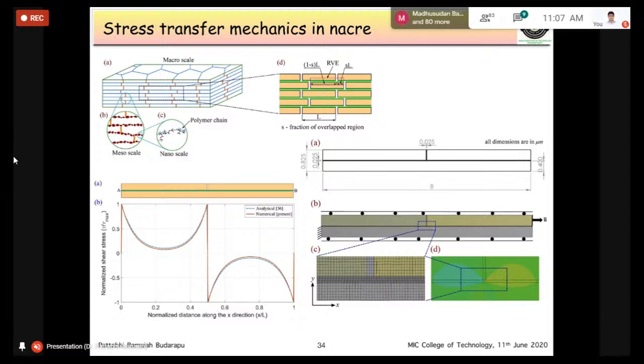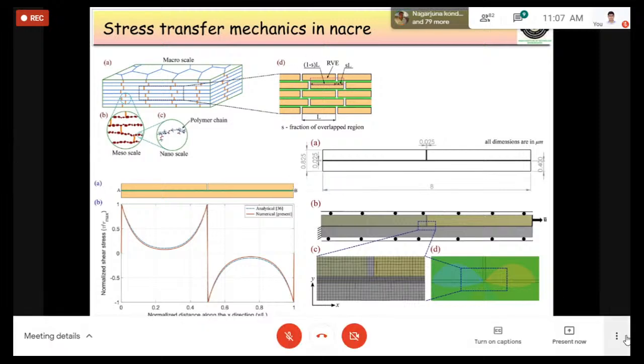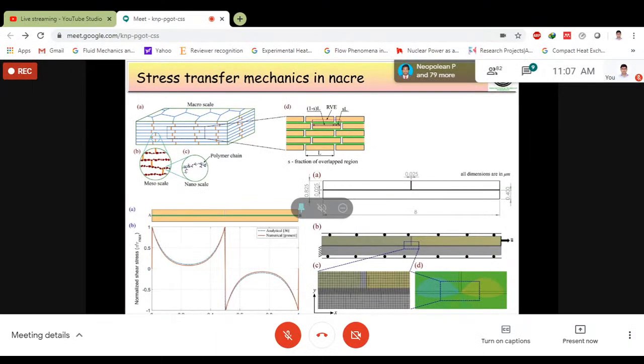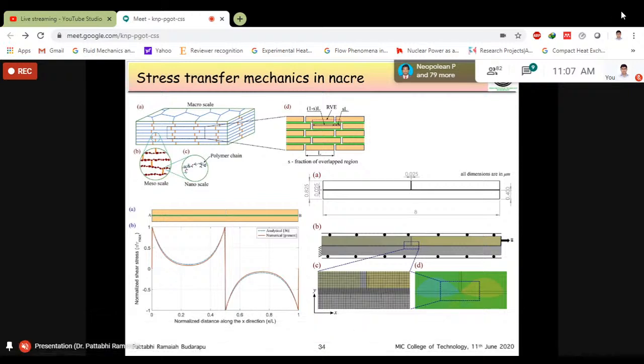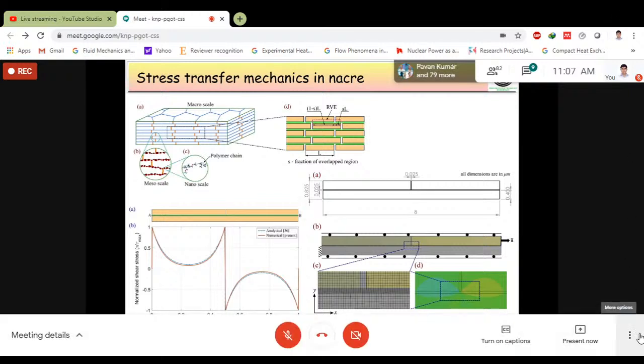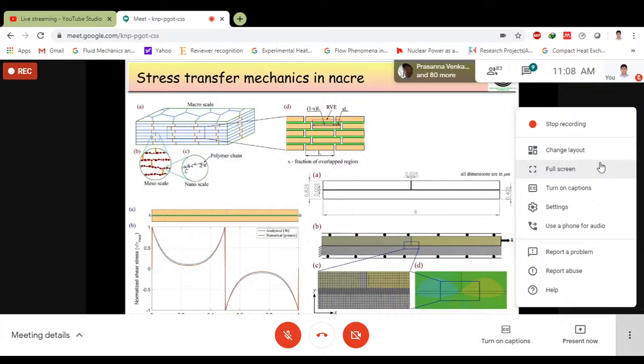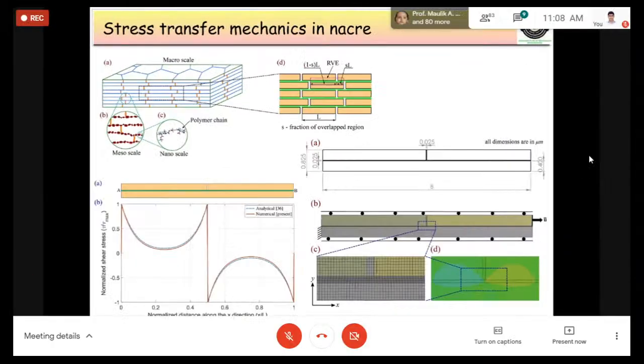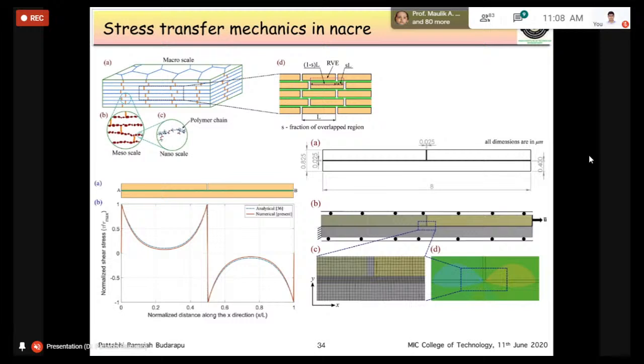Since we considered 50% overlap, in other words the size of the top tablet is equal to half the size of the bottom tablet, more or less, because the interface thickness is quite small at 0.025 micron, the stress distribution in each tablet is exactly symmetric. I can see symmetric behavior with peaks occurring across the edges - left edge, middle edge separated by the interface, middle of the top tablet, and right edge. So across the edges the stresses are peaking, and in the middle they are quite flat.